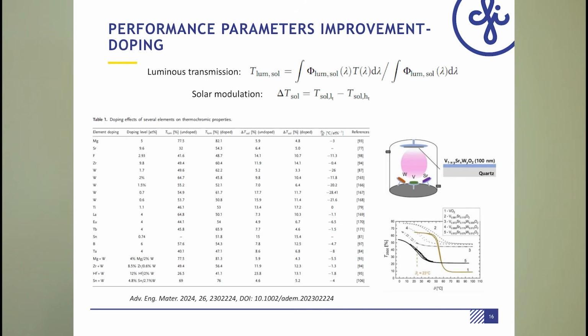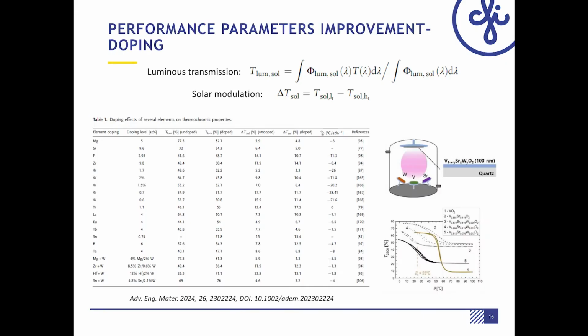There are three main parameters which can be used to characterize and compare thermochromic vanadium dioxide coatings. First of all, that is luminous transmission. That means how transparent the film is. The higher transparency, the better. Second one is solar modulation, which shows difference between active and inactive state, or ability to block light. And last is phase transition temperature. The closer it is to room temperature, the better.